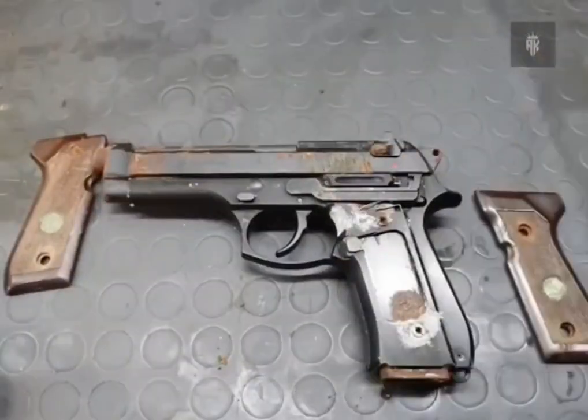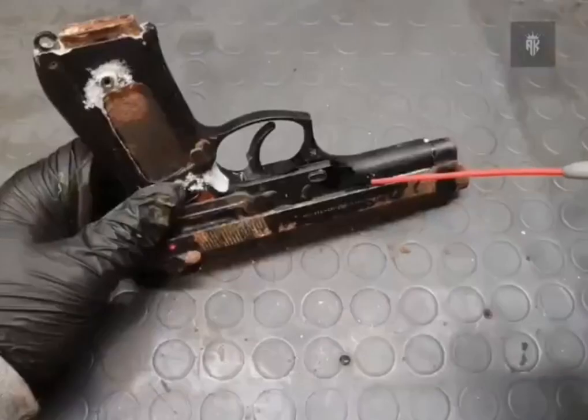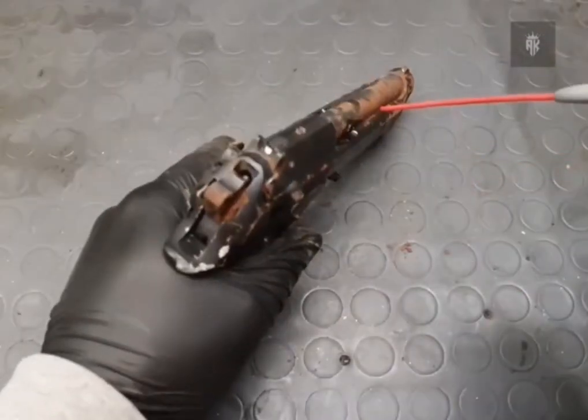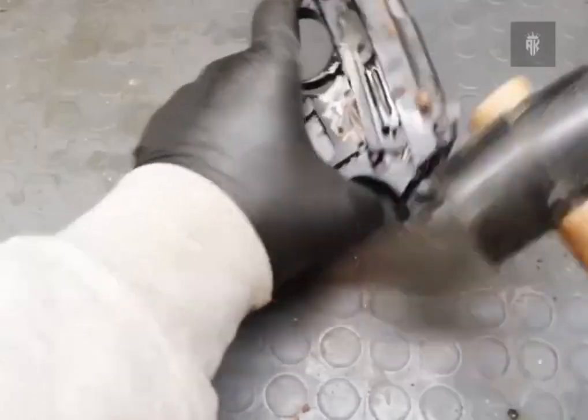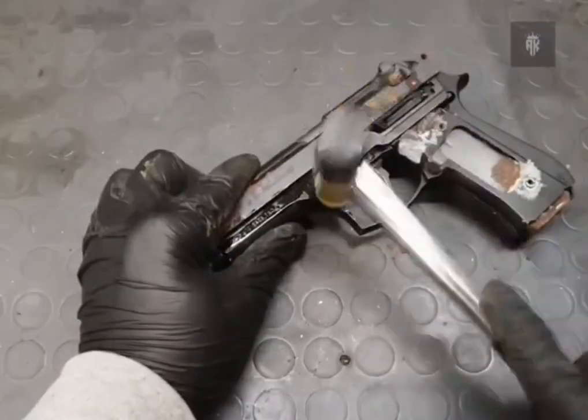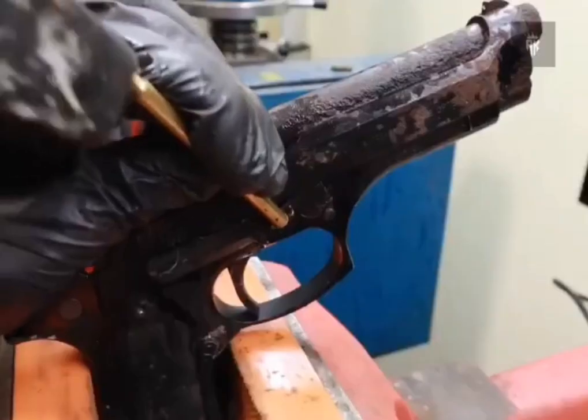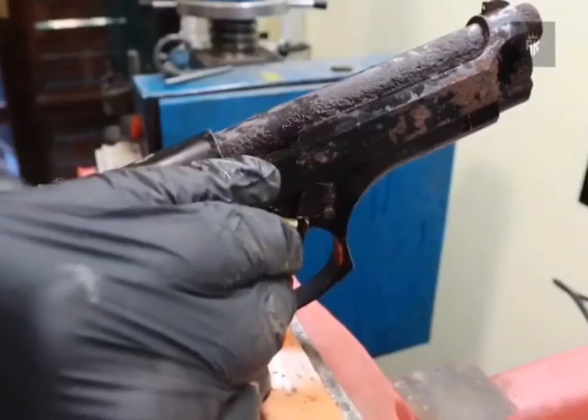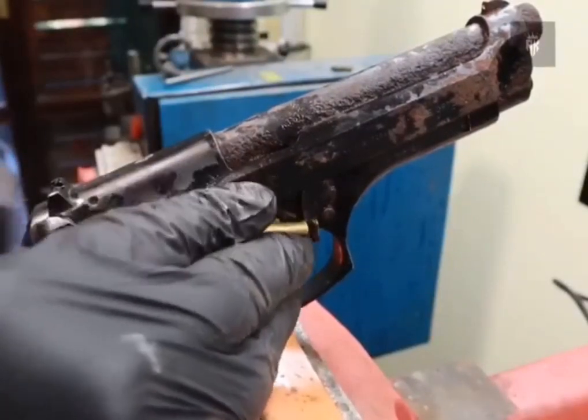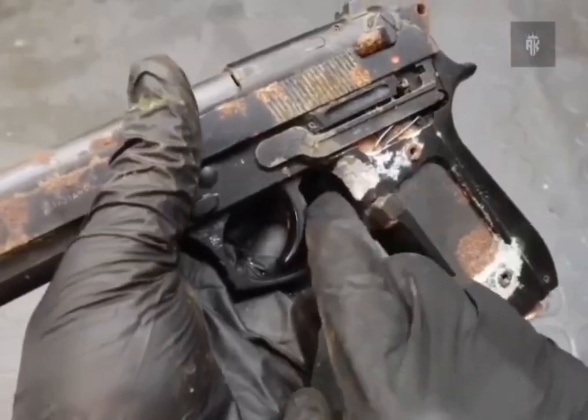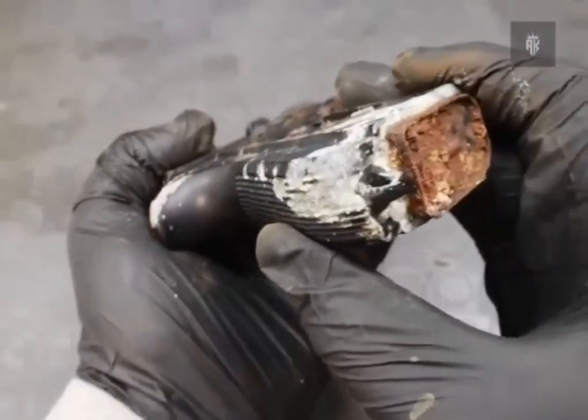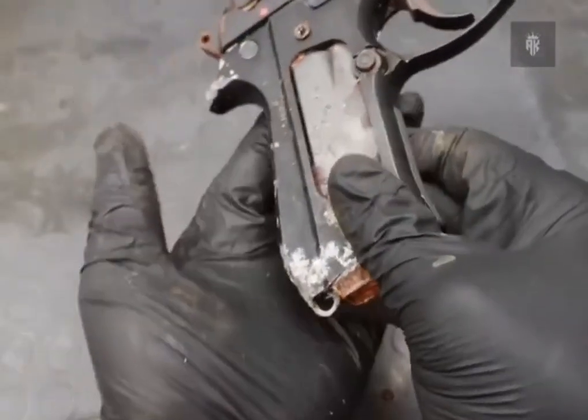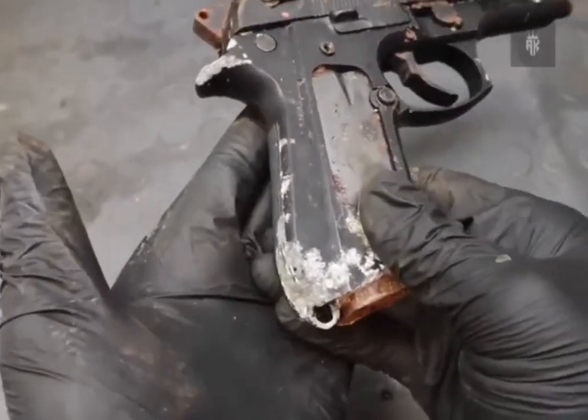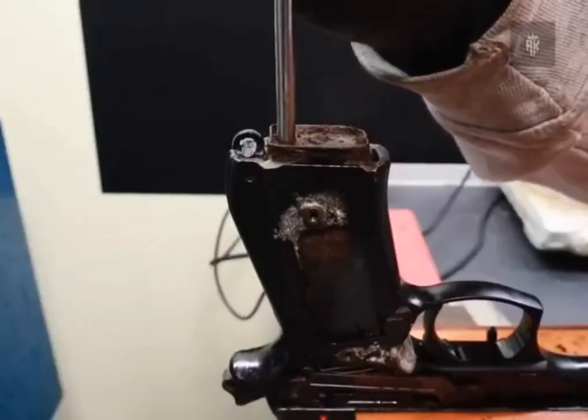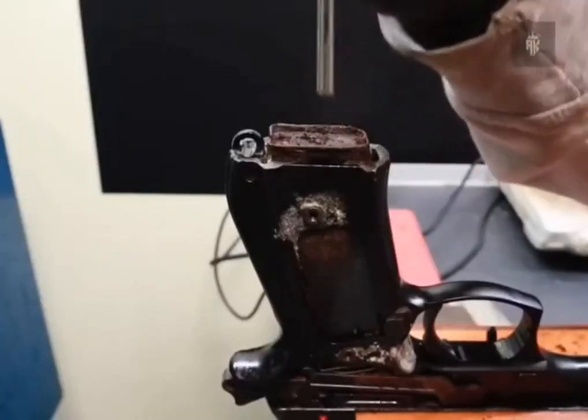While we try to do that, look at the frame. It is made out of anodized aluminum alloy, probably of the 7000 series, meaning it is alloyed with magnesium and zinc. It is the strongest type of aluminum alloy, but unfortunately this somewhat limits the corrosion resistance in very aggressive environments. For this reason, a hard anodizing treatment is done to protect it, as well as coloring it black. However, once corrosion makes it through the anodizing in one spot, it starts eating away the underlying material, resulting in this typical cratered look. The aluminum base plate of the magazine was completely dissolved, so that only rust was holding the spring in place.